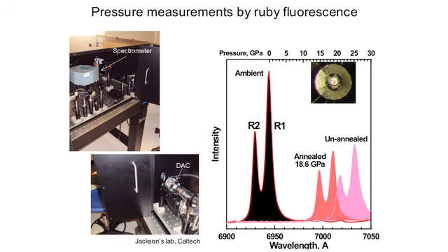So these changes in wavelength that are a result of me tightening the screws can be correlated with a pressure. And of course, then pressure can be correlated with the depth inside of the Earth. So now we know what depth or pressure our mineral is experiencing, and we can keep it there. So that's the elegance of these cells: the properties that we're interested in, we can measure at very controlled pressure or depth steps and temperature.